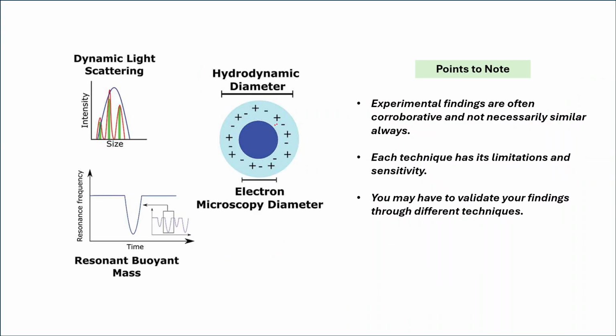But before that, suppose you did nanoparticle characterization using scanning electron microscopy and you found this size. But scanning electron microscopy is done in a dried state. I just now told you to take a glass slide, drop a sample on it, dry it, and then analyze. But dynamic light scattering is done in a suspension state. Suppose you are putting 1 ml of sample, which is carrying your nanoparticles. So that is why there's a difference in the diameter.